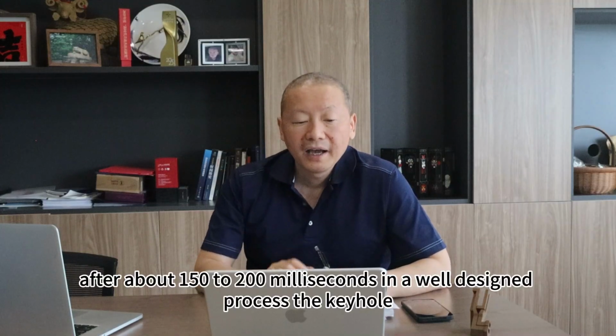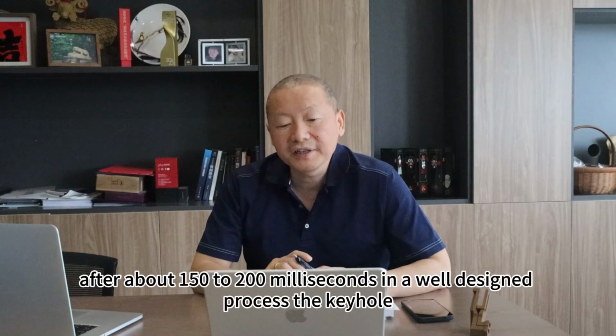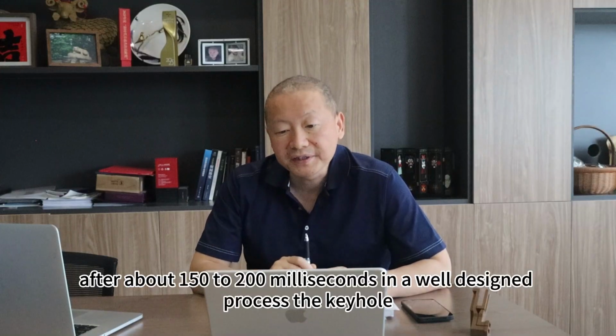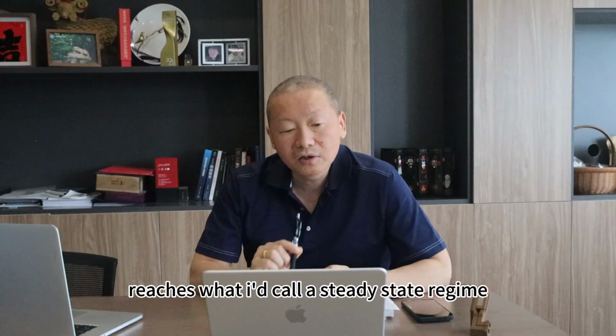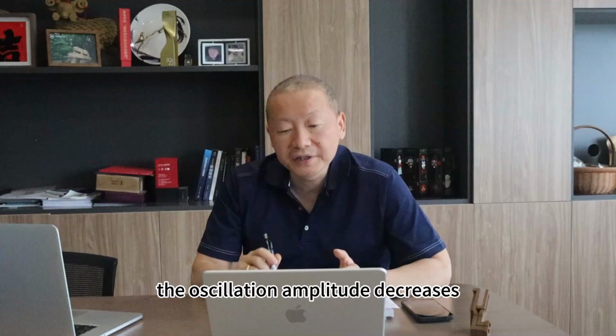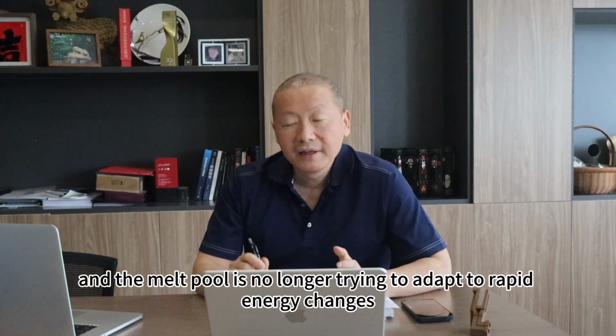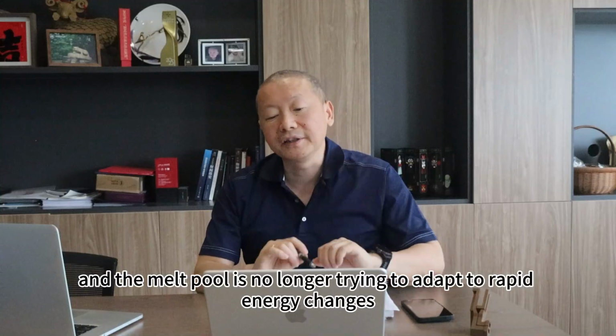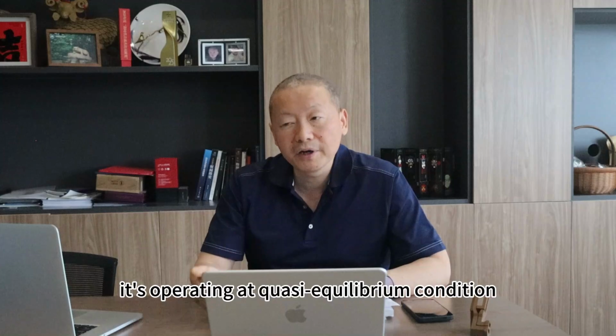After about 150 to 200 milliseconds in a well-designed process, the keyhole reaches what I'd call a steady-state regime. The oscillation amplitude decreases, spatter rate drops, penetration depth stabilizes. The melt pool is no longer trying to adapt to rapid energy change. It's operating at quasi-equilibrium condition.